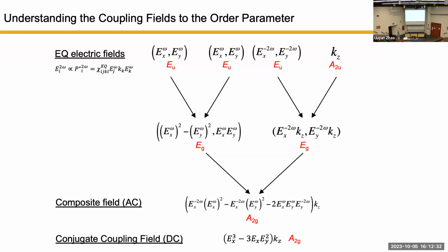Yeah. So, you've shown us here that linear optics can't access this. What are these? If they do linear optics, it's as if there's no phase transition. So basically, I record the intensity of reflectivity. I will just see a flat line as a function of temperature. The reason is because for linear optics, it cannot tell the difference of the so-called bar 3 versus bar 3M. Linear optics, the tensor of these 2 are exactly the same.